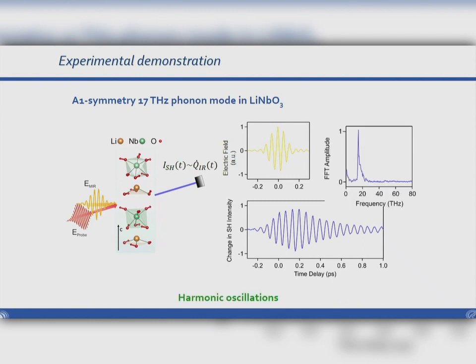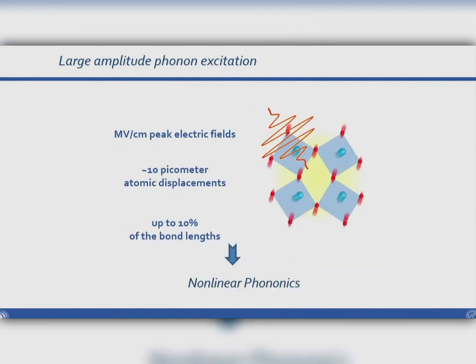And you see a mono frequency response as shown here in the Fourier transformation of that curve. However, we are able to produce very intense light fields at these frequencies. We can easily reach megavolt per centimeter peak fields. And this will induce atomic displacements of the order of 10 picometers maybe. This is up to 10% of the bond length that you find in these materials.